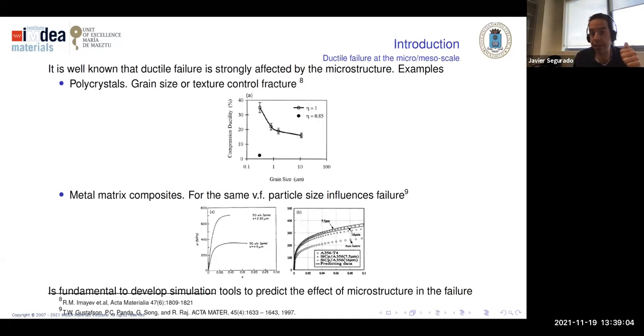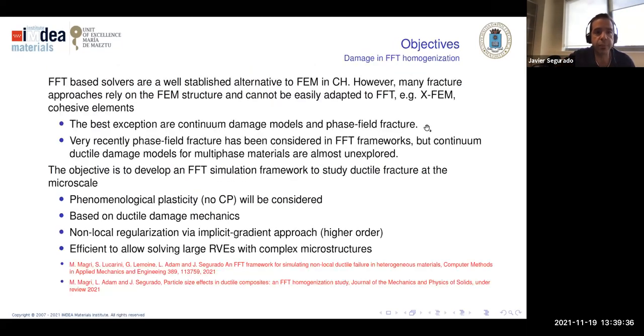Nevertheless, it is well known that the microstructure influences the result. We have seen that it happens in the monotonic and also in the cyclic response, but it also affects the fracture, the static fracture. In the case of a pure polycrystal, we can see that the grain size in this graph has an influence on the ductility. And in the case of metal matrix composite, even if we have the same volume fraction of precipitate, the size of the particles has an influence on the ductility. So again, it's fundamental to understand this, and this goes beyond what we have seen up to now.